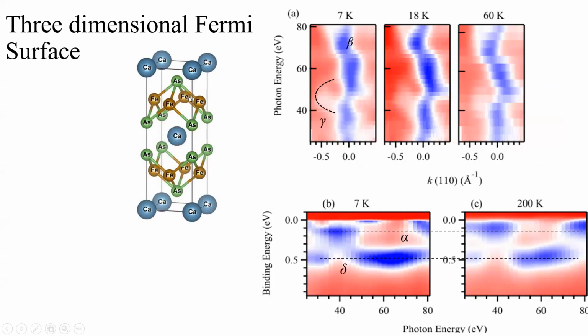As I said, these iron and arsenic layers are the only layers which contribute close to the Fermi energy. Now, when I dope cobalt at the iron position, since cobalt has a smaller atomic radius, the hybridization between iron and arsenic will increase. At the same time, the iron–calcium bond length will decrease, so you can expect significant hybridization along the kz direction, which was not present in the parent compound. That can lead to a kz dependence of the bands.